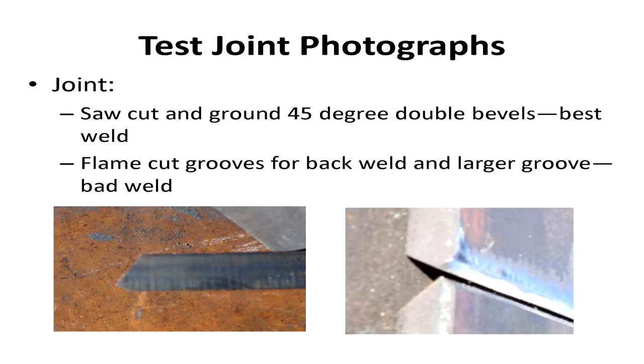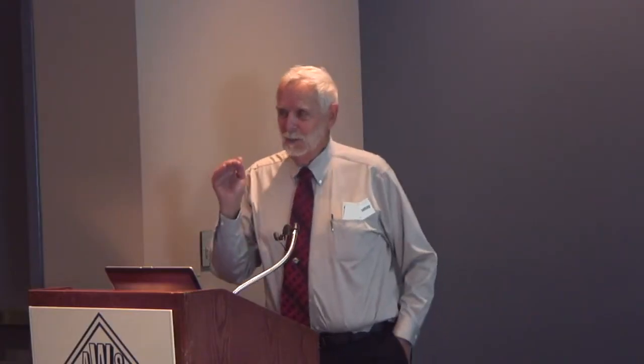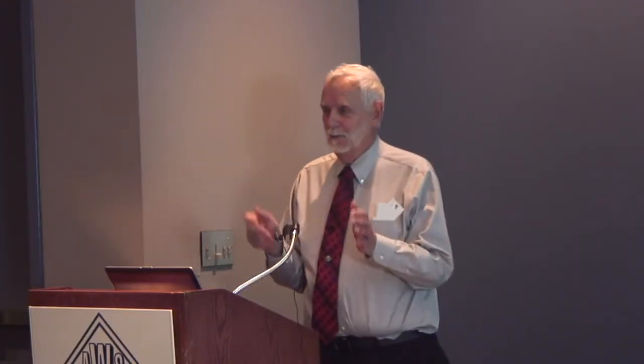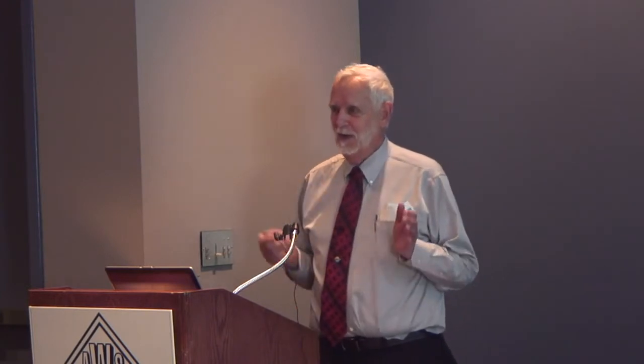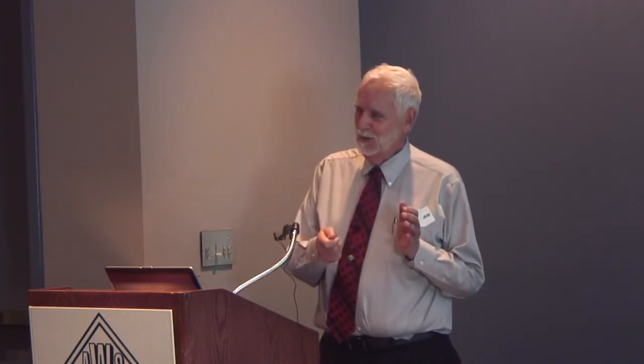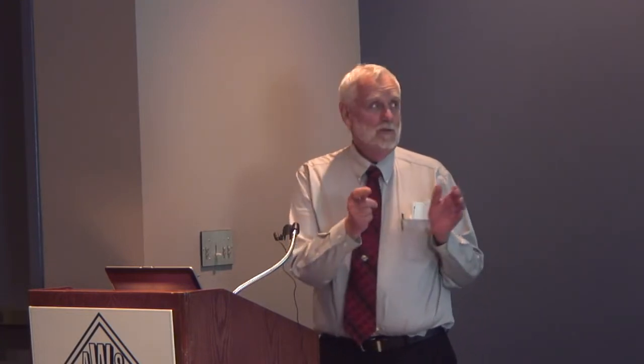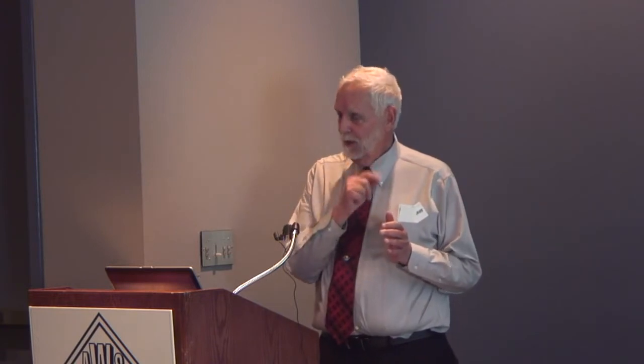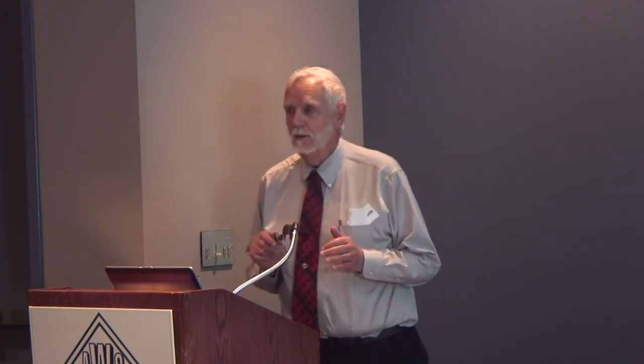This is the bevel I used, and then I'd flame cut the bad one. Now, we're putting so much heat into it that quench and tempered, it's like taking your pocket knife and putting it in a campfire and leaving it for an hour, because it's tempered, and you put the heat into it, and you're going to mess it up. You're going to anneal it. Well, that's what happens. You flame cut this material, that's what happens. Plasma cut's okay. Flame cut's bad.